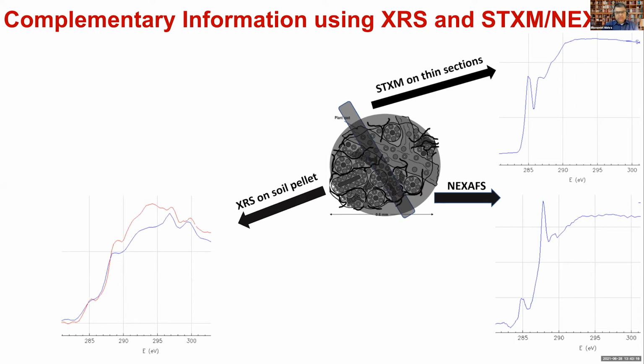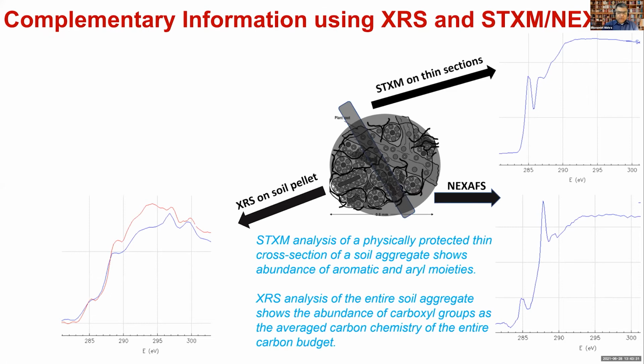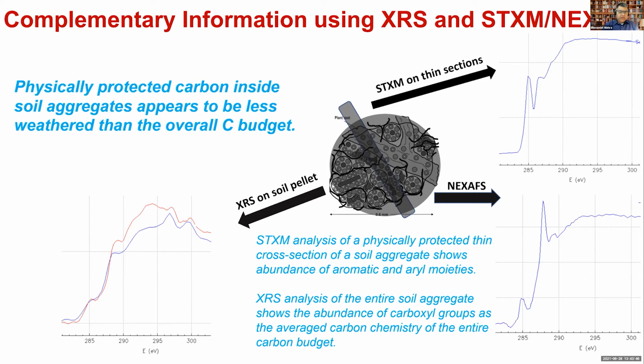What is happening is that STXM provides information about carbon locked inside the soil aggregate, which has never seen ambient conditions, and hence we see mostly an abundance of aromatic and aryl moieties. Whereas XRS shows the average of the overall carbon budget, and that shows an abundance of carboxyl groups. So clearly, the physically protected carbon inside the soil aggregate appears to be less weathered than the overall carbon budget. Now, this finding should not surprise anyone, but indeed this is a really neat experiment that we're able to conduct and get this answer.